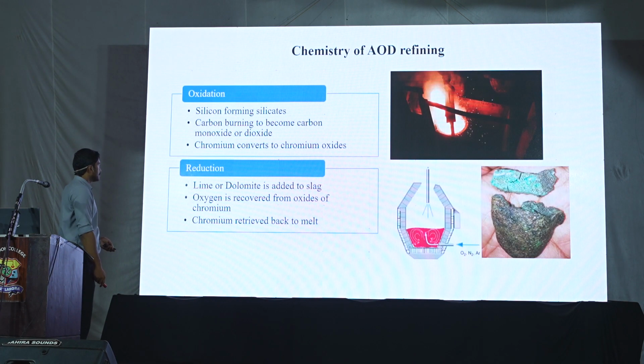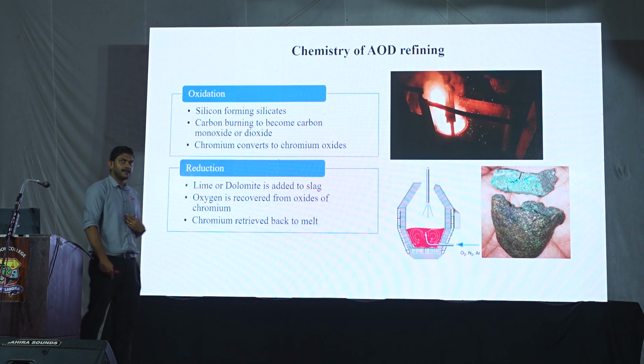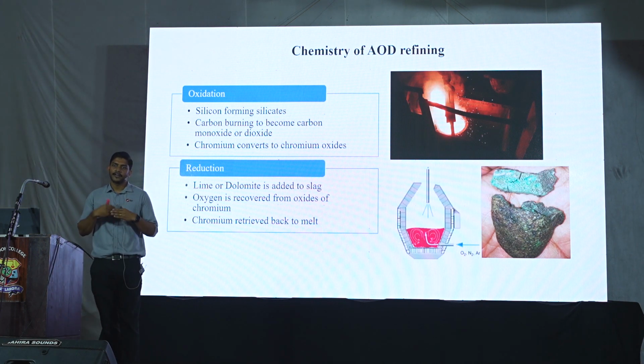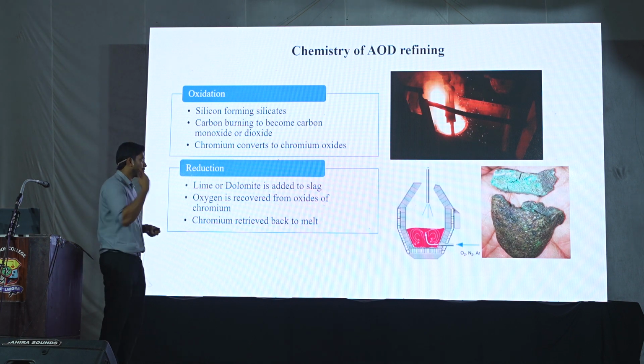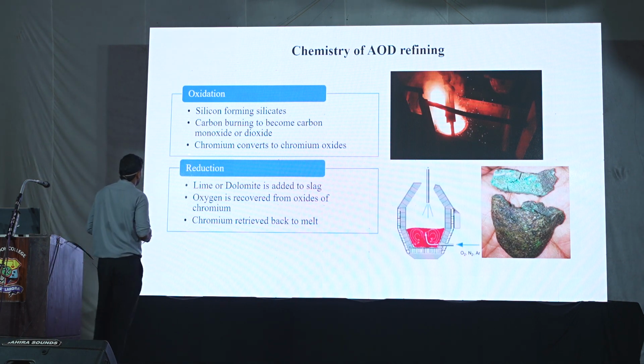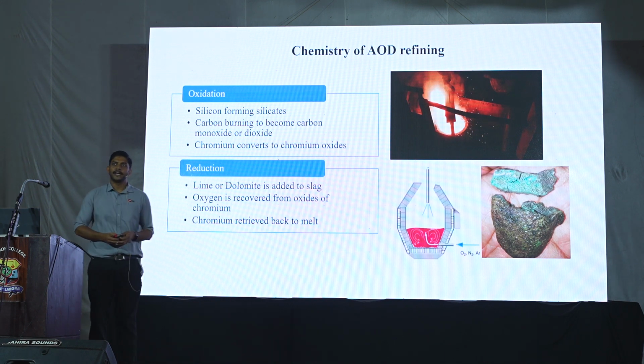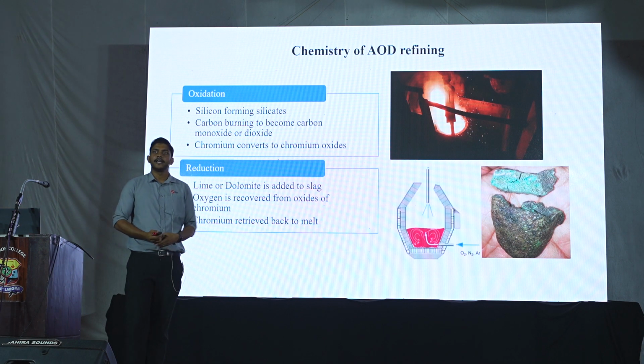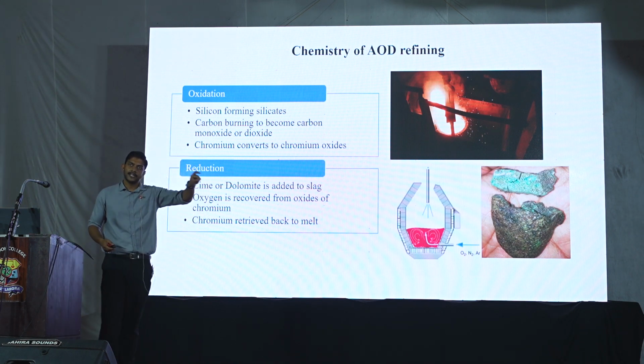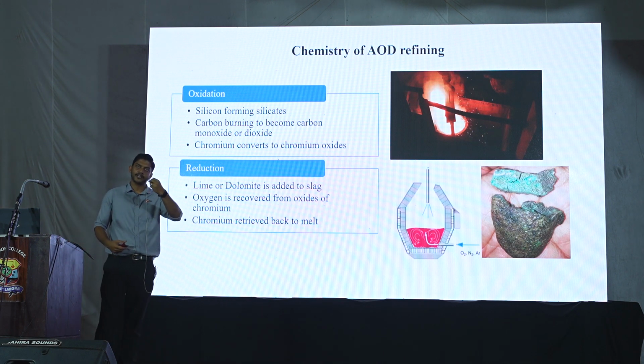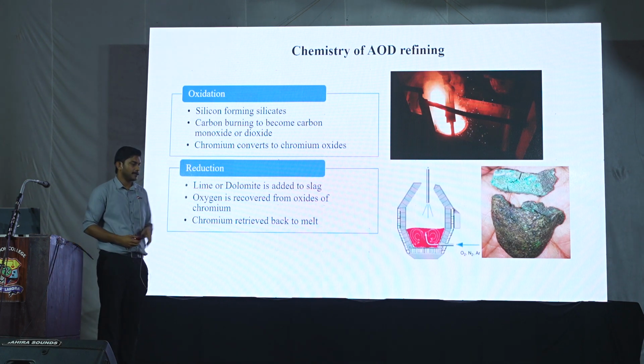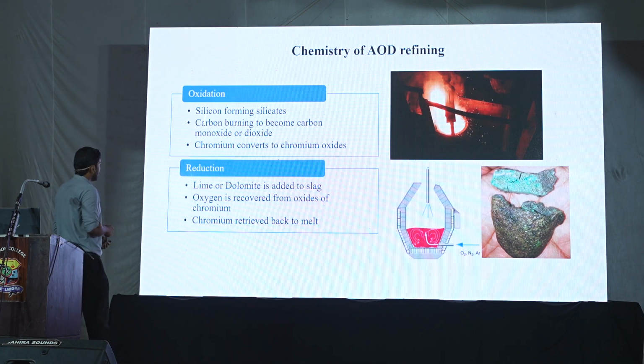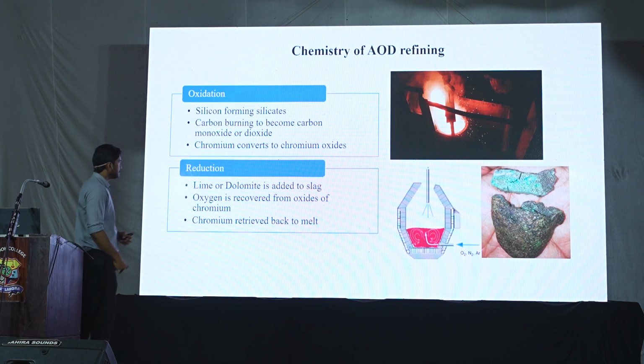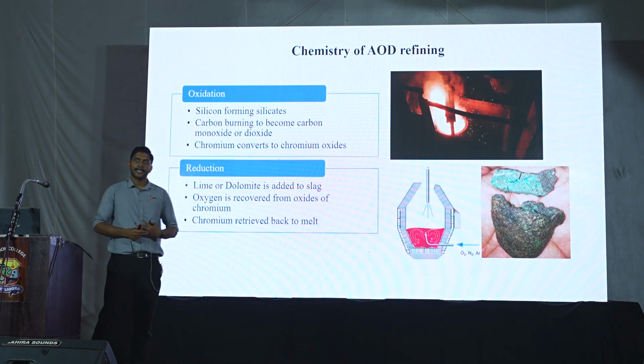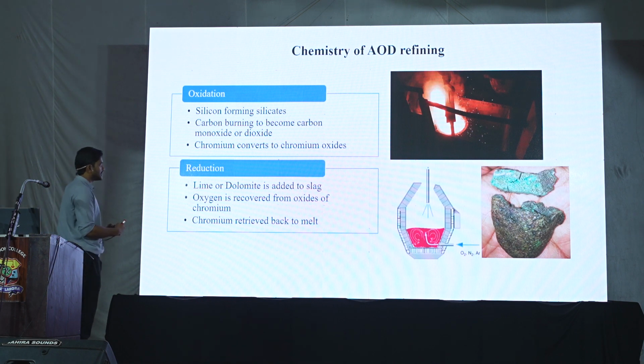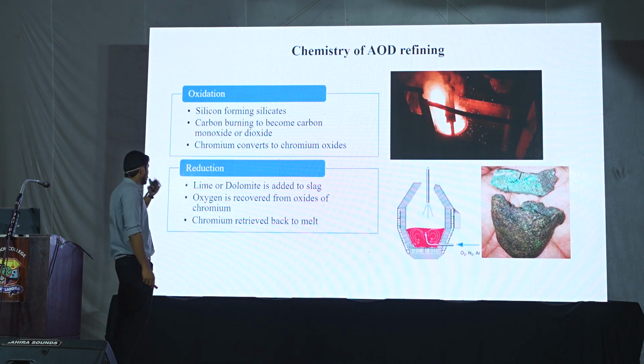materials present inside. Basically, the reactions that happen are, initially, we need to purge all the impurities, or whatever is affecting the corrosion resistance. First, carbon out, silicon out, and then there is a much needed element inside, chromium, but that also has an oxidizing characteristic and goes out into the slag, the impurity layer, the oxidized layer and the reactive products formed above the molten metal. From that layer, we have to get the chromium back into the metal, and that is the next stage. We add calcium, which reacts with the oxygen, and basically the slag will be removed before more chromium comes into the slag.